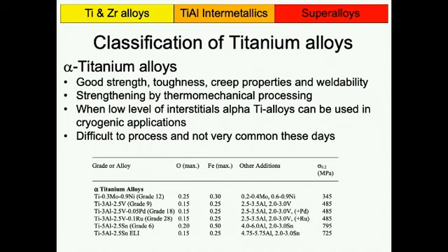And then you might have some other additions, but here are the additions, so it's a more accurate number. You can see something you might not be aware of when they talk about a titanium 5 aluminium 2.5 tin. You might think, okay, it's 5% aluminium, but you can see that very often it's a range in reality. So it's 4 to 6% aluminium. Although actually that change from 4 to 6% we now know has a massive effect on mechanical properties.